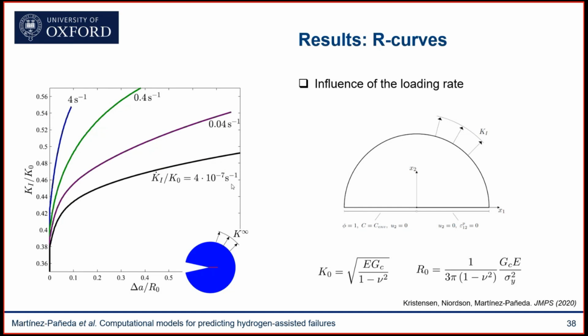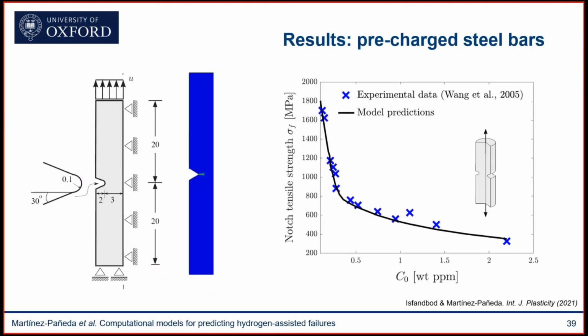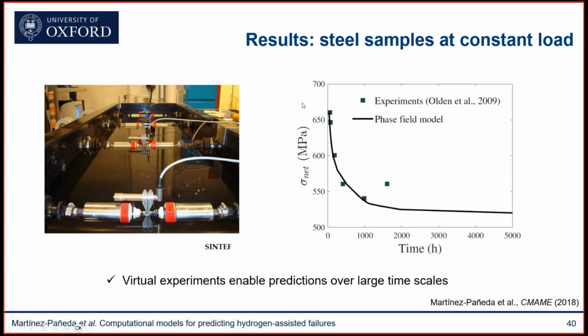But we can also be quantitative. These were qualitative observations. Here's a comparison with experiments on pre-charged steel bars. These are high-strength steels, and you can see that the measurements of notch tensile strength versus hydrogen content are in very good agreement with the model. This is a set of interesting experiments conducted at SINTEF.